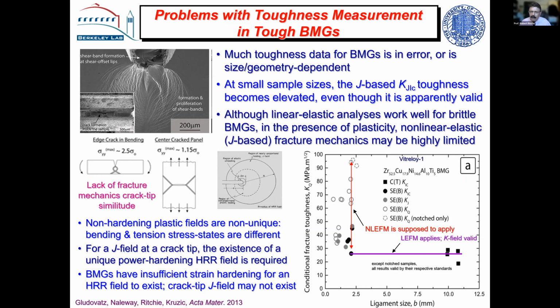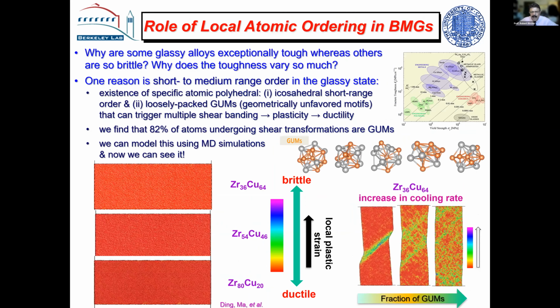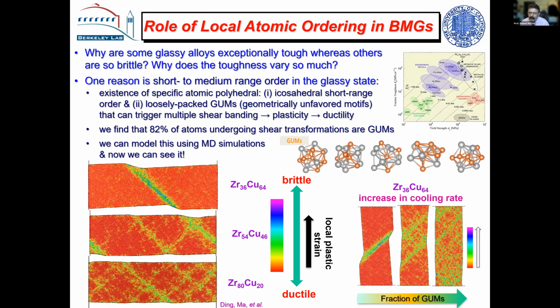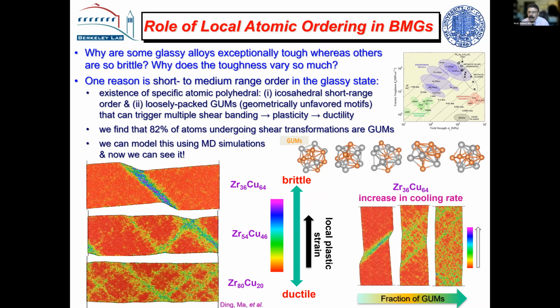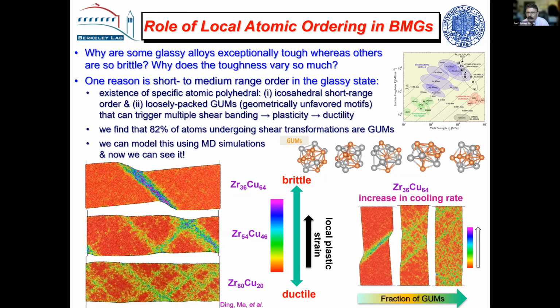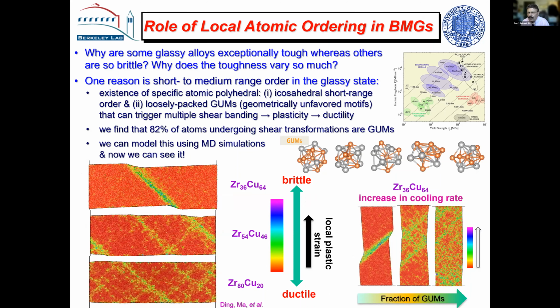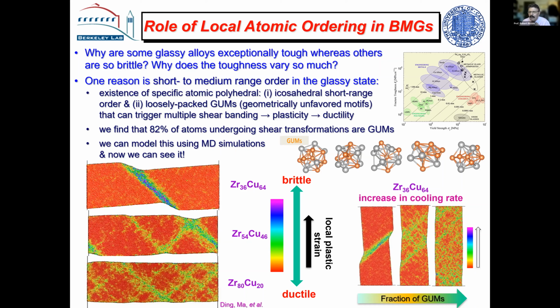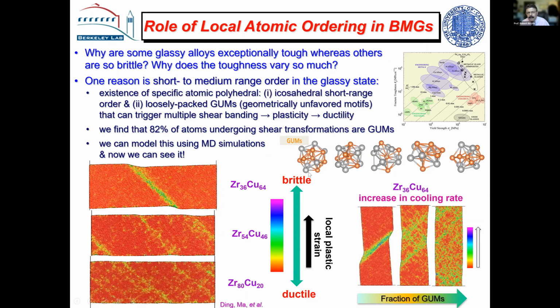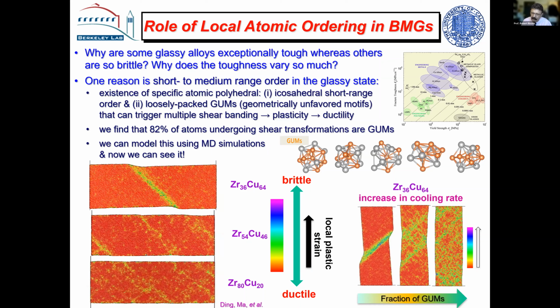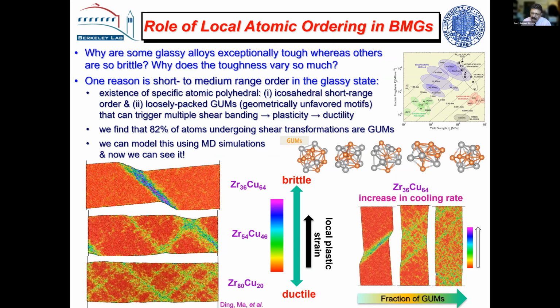There's another reason, though, which I think is very interesting, and that is what causes these shear bands. Now, in metallic glasses, if you anneal them, they become more brittle, and if you quench them, they become more ductile. And there's this phenomenon called rejuvenation, which seems at first sight to be counterintuitive. But this is a theory that came out of basically Evan Ma, that in these amorphous states, you get little motifs of atoms. They're little regions of icosahedral symmetry, five-fold symmetry, which make them stable. And these are basically motifs, and you can predict them and you can actually measure them.